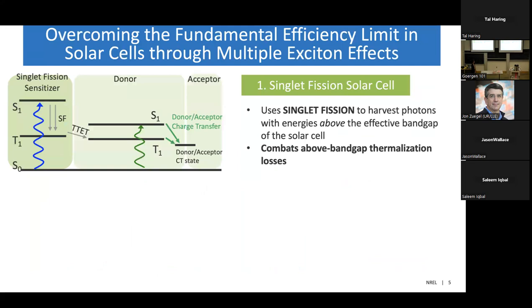So let's take a look at how both of these multiple exciton effects can improve the performance of our solar cells. So in the first example, I want to discuss singlet fission solar cells. So here I have a very conventional organic solar cell heterojunction where we have an electron donor and an electron acceptor. And both of these materials can absorb light independently. And then at the interface between them, we have a charge transfer state that turns those bound excitons into free charge. Now, in the singlet fission solar cell, we add an additional component that's able to undergo singlet fission.